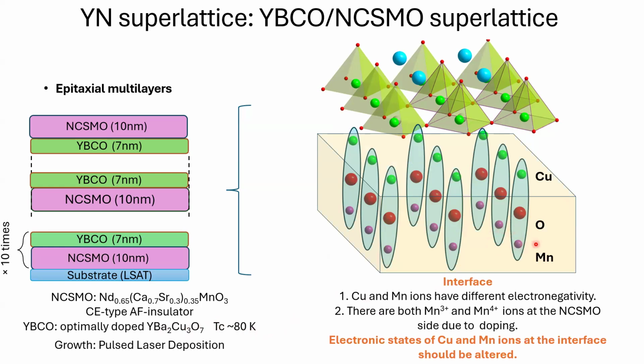In this case, we see that there is a connection through the apical oxygen between the copper and manganese ion. This connection immediately leads to a strong alteration of the electronic state of both the manganese and copper ion. There are a few reasons for this behavior. One of them is that the copper and manganese ions have different electronegativity. Another is that there are two types of manganese ion, because of the doping of the manganite layer, we have manganese 3 plus and manganese 4 plus sites. So the electronic state of the copper and manganese ion at the interface should be strongly altered.